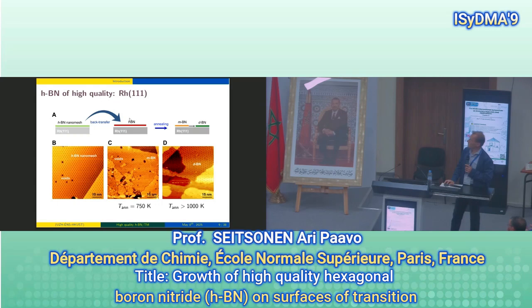They put it on the rhodium, and this is the so-called TBN, the transferred BN. But it has more defects, for example, as you see here. What they then do is another annealing, and they see that they have this so-called distilled hBN, and it's of the same quality as the original one. So the idea is to show that you could grow this hBN on one substrate, in this case mostly rhodium-111, and then transfer it to another surface. By annealing, you get this metastable hBN first, and then when you go high enough in temperature, you get this distilled, or again, high quality boron nitride on a different substrate.